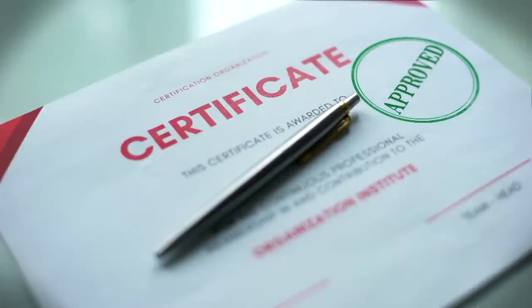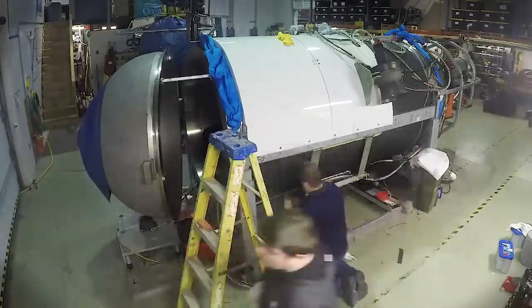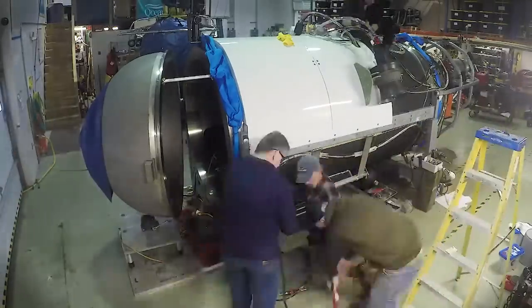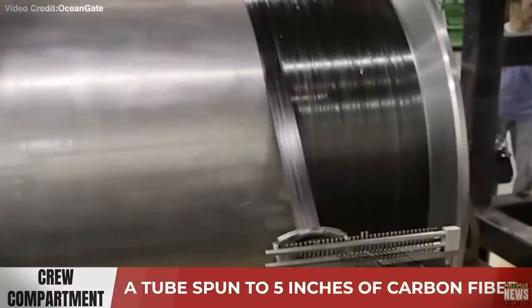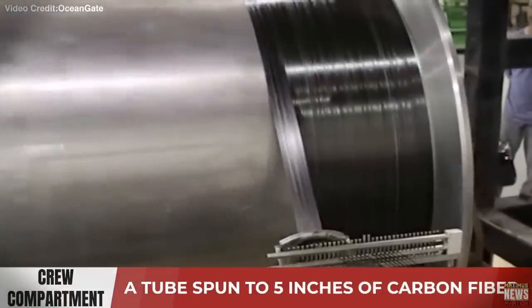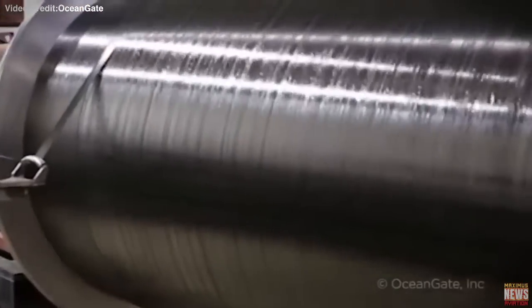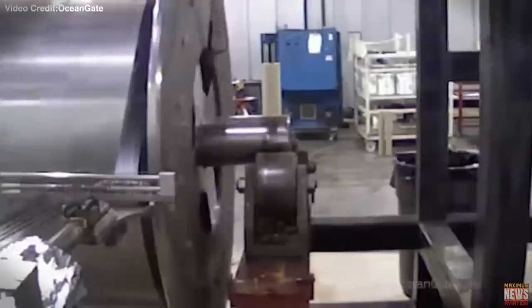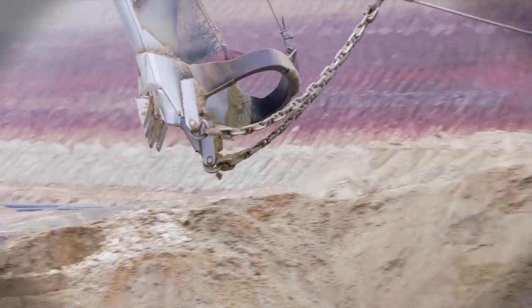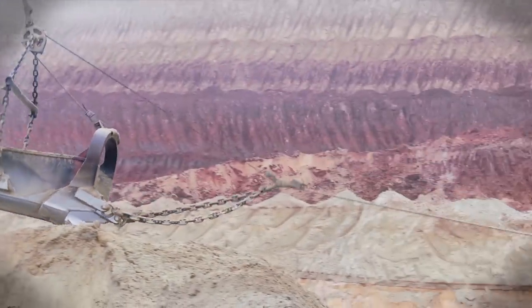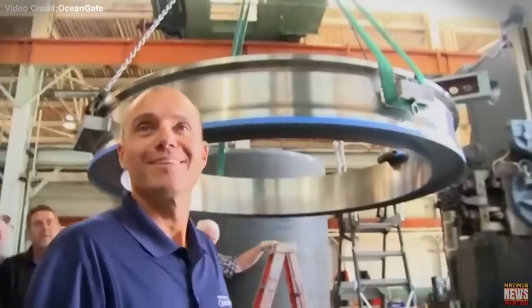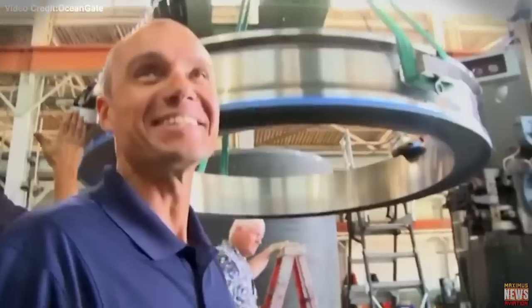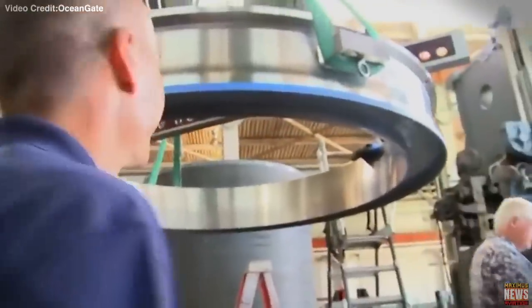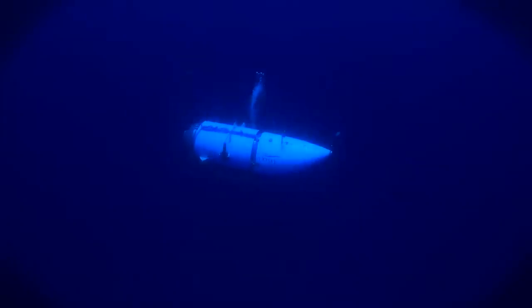Instead, the submersible utilized a carbon fiber cylinder, a structure that was developed in collaboration with Boeing and has posed its own challenges. The domes of the submersible were constructed using 3.25-inch thick titanium. The carbon fiber, along with a titanium face and interface and the dome, were meticulously assembled with precise tolerances on the surface. Notably, the submersible's design ensured that no pipes, wires, cables, or tubes entered the carbon fiber section. The absence of thorough testing and certification procedures raised legitimate concerns regarding the construction of the Titan submersible.